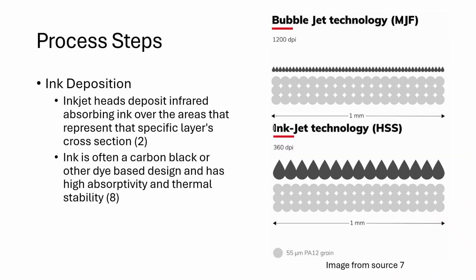Another thing to look at is the dots per inch between the multi-jet fusion and high-speed sintering processes. The dots per inch for a process like multi-jet fusion is typically much higher than high-speed sintering, but the limiting factor for print resolution is typically not print head DPI, but is actually powder particle size.